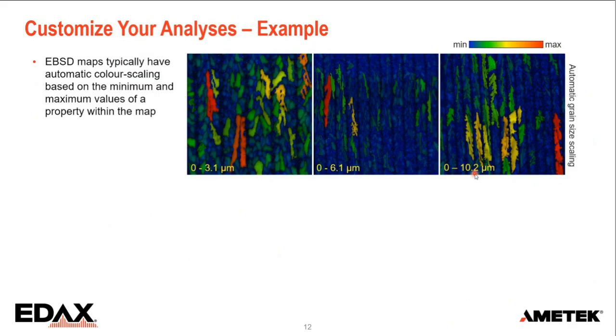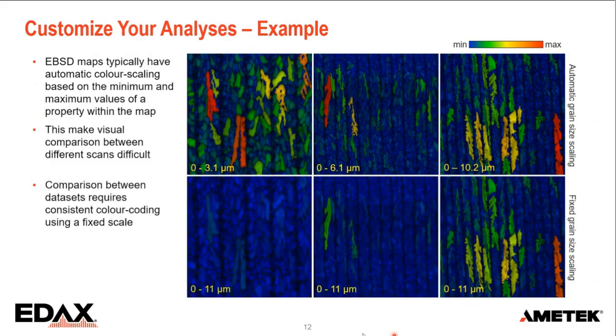And that means if you have multiple data sets, you want to compare the data, what you need to do is fix the scale. And in this case, I have set the scale from 0 to 11 micron. So now all my maps are shown in the same color coding. And now you can really see an honest comparison between these maps. So that's something to be aware of if you do EBSD analysis. You're looking at a color coding. The color coding is typically based on whatever you have in your display from minimum to maximum. And if you do that between different data sets, you can have quite a variation.